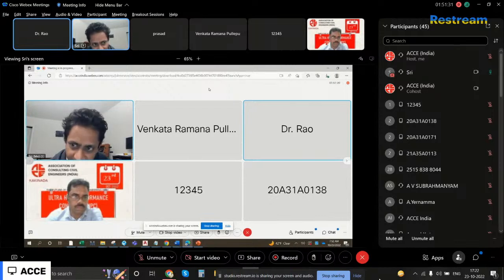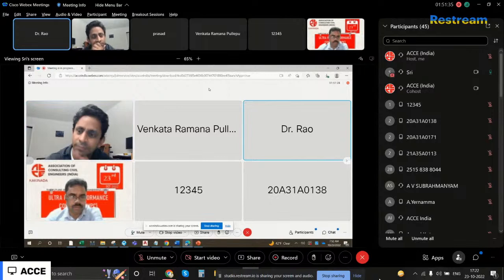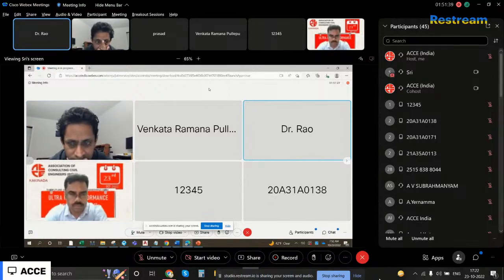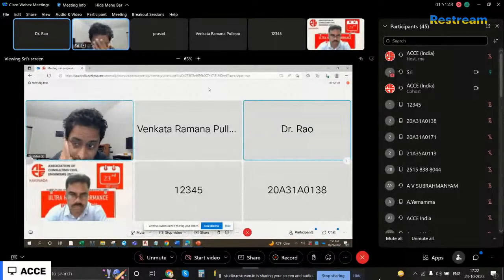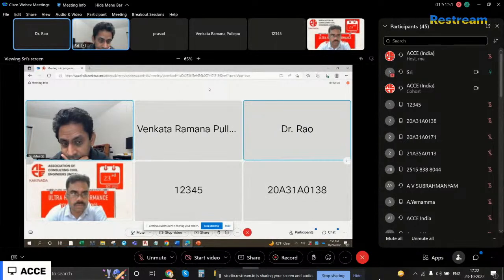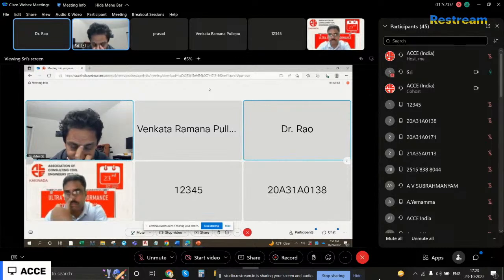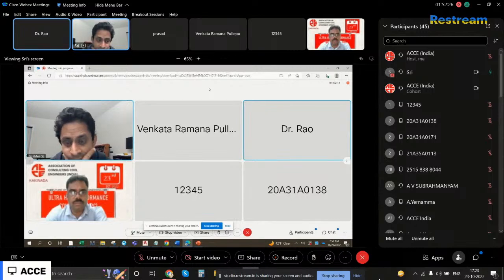Regarding eliminating the coarse aggregate, what we learned in our MTech structural engineering from my guru, Professor Shashkirao sir, is that especially in the case of high strength concretes, not only the strength of the coarse aggregate plays the important role. It is the transition zone between the coarse aggregate and the matrix, the interfacial transition zone, which governs the strength of the concrete. So if you minimize the coarse aggregate, there is an advantage in that it minimizes the transition zones, first of all. And second, the flowability and segregation problems, the associated problems of concrete, will be eliminated with no coarse aggregate concrete. That is what we learned from our guru, Professor Shashkirao sir.